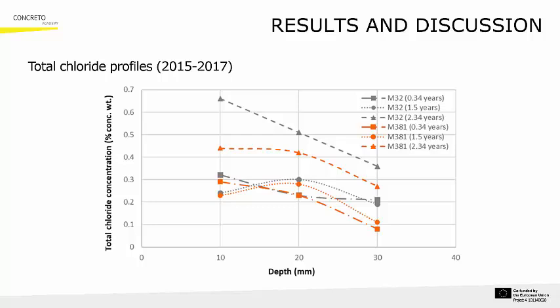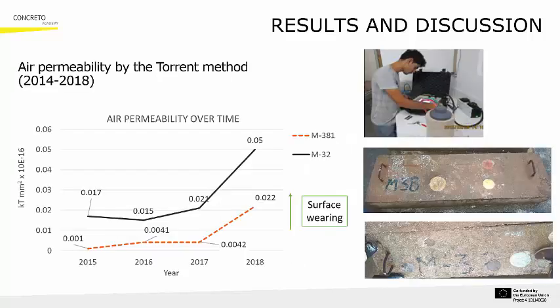It should also be noted that the differences in chloride content between the two concretes increase over time. This observation will be addressed in the next slides. The air permeability using the Torrent method was another test applied on the cores extracted from the elements.